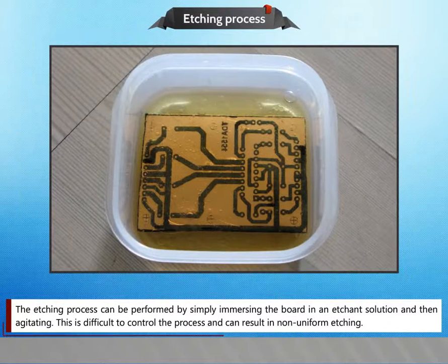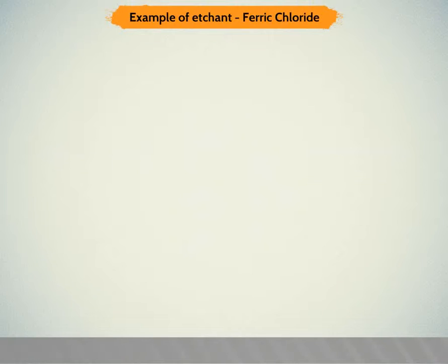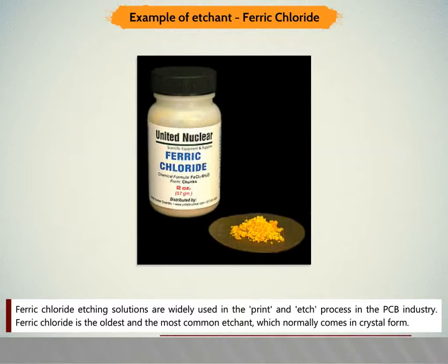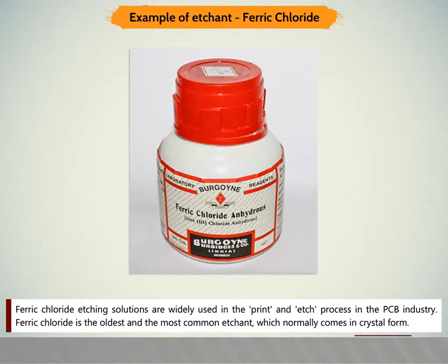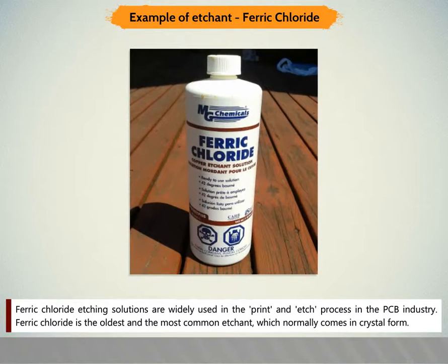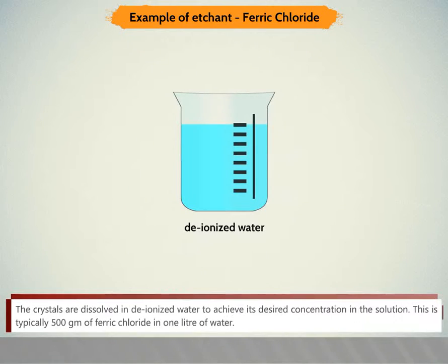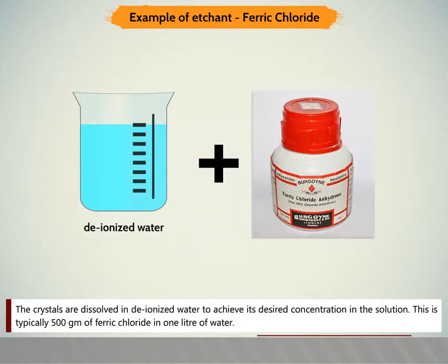The etching process can be performed by simply immersing the board in an etchant solution and then agitating. This is difficult to control and can result in non-uniform etching. Example of etchant: ferric chloride. Ferric chloride etching solutions are widely used in the print and etch process in the PCB industry. Ferric chloride is the oldest and the most common etchant, which normally comes in crystal form. The crystals are dissolved in deionized water to achieve the desired concentration in the solution. This is typically 500 grams of ferric chloride in 1 liter of water.